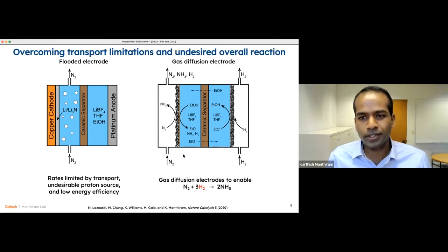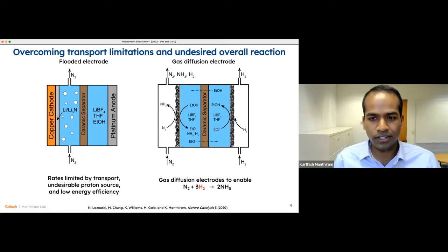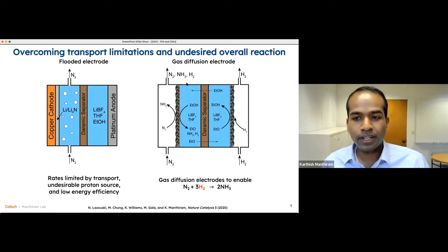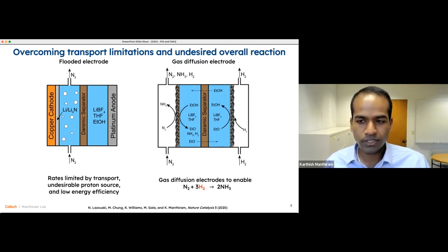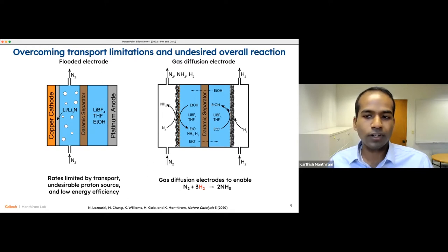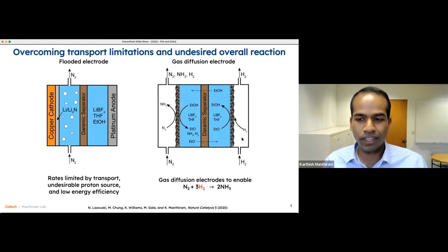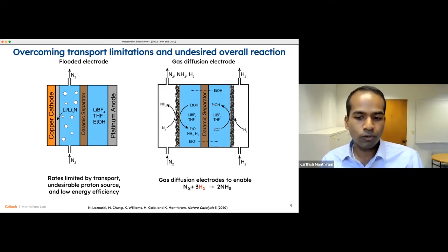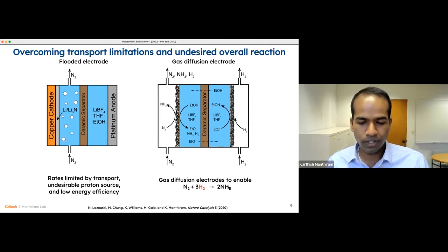And we put forth that if we were to use gas diffusion electrodes at both the cathode and anode, that these challenges could be overcome. The gas diffusion electrode would provide efficient contacting of the gas phase nitrogen with the liquid phase electrolyte, and the solid phase support here, which is bringing in the electrons that are needed for the reduction. The same thing could be implemented at the anode as well, a gas diffusion electrode, which allows for contacting of hydrogen, which we introduce, and that by oxidizing hydrogen, we could overcome the oxidation of THF and ethanol, that really hydrogen should be our proton source here. And so this would then enable this overall reaction of nitrogen and hydrogen going to ammonia, as long as the hydrogen comes from a sustainable place.